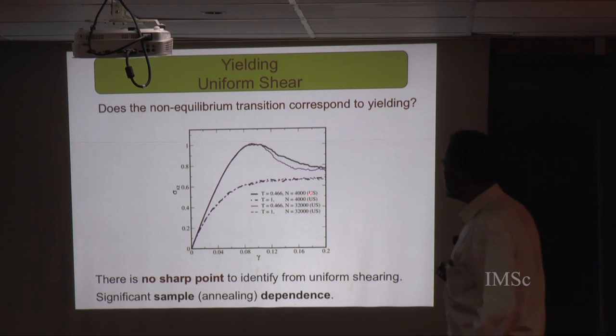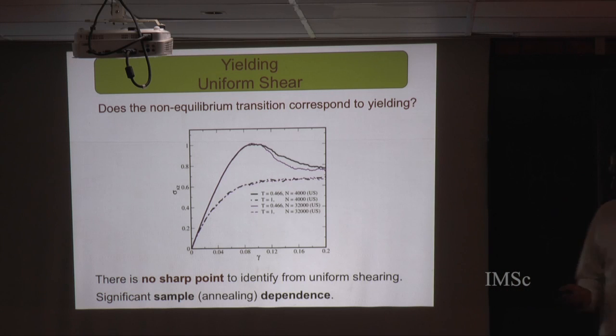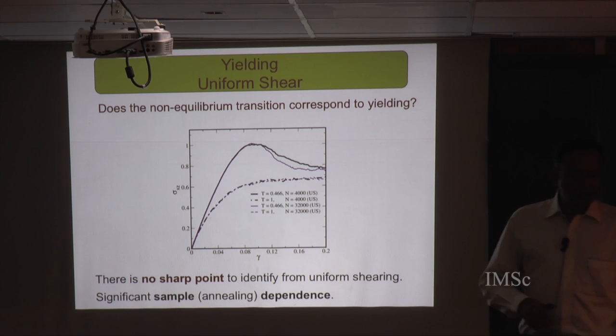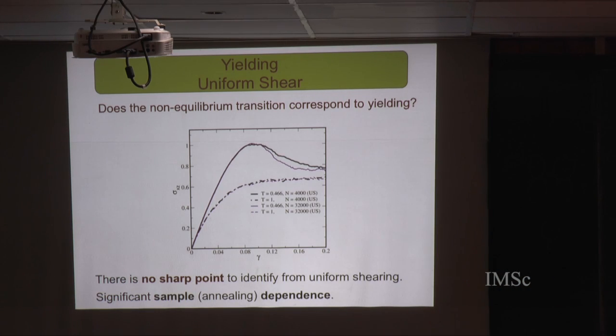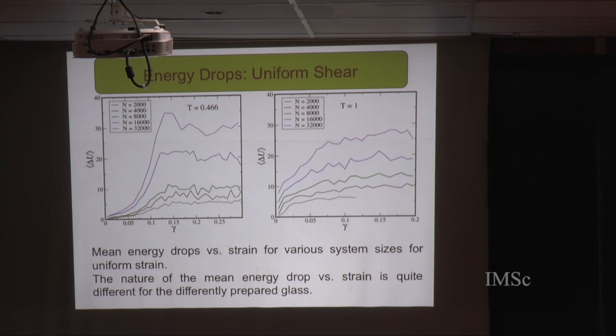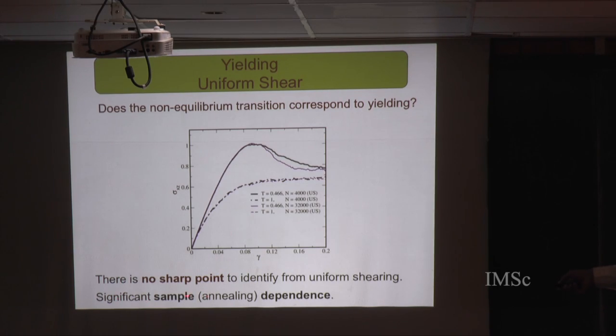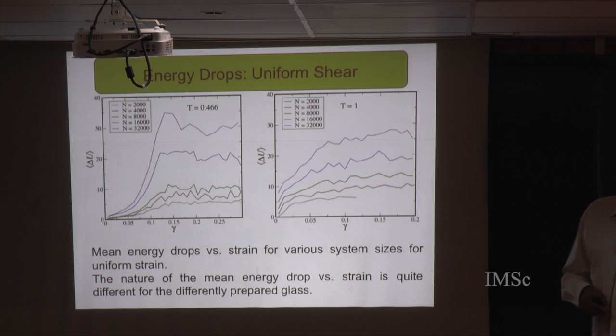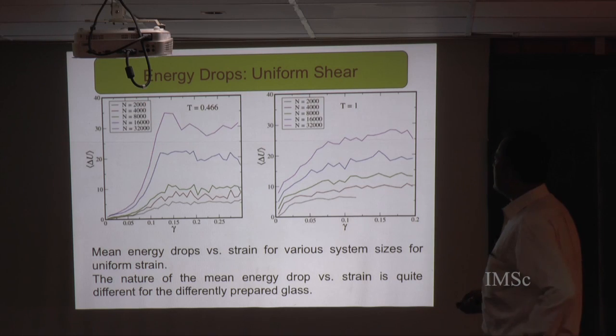On the other hand, if I look at a poorly annealed glass, it's in fact hard to pick out any particular feature which I can associate with yielding. So there's no sharp point to identify if one looks at uniform deformation. What we ask is - and the second point - is that there's a very significant sample dependence. Depending on what glass you start with, you have very significant sample dependence, and this is further illustrated by looking at various system sizes and the mean energy drops as a function of strain for both the well annealed and the poorly annealed glass.